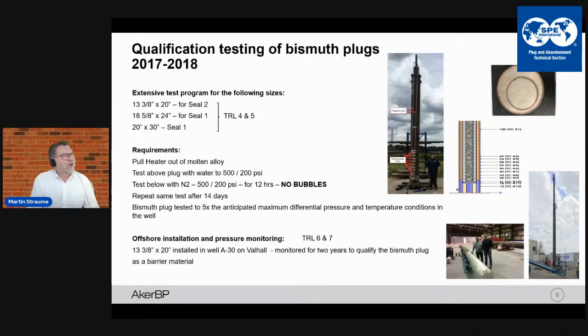So we decided to try bismuth, but before we tried that out, we needed to have a test program. We went to Houston and teamed up with BiSN at that time. BiSN was still there, and we wanted to make a large bismuth plug. This was larger than any bismuth plug they had made before, so we needed to test that out. We were going to have it shallow, as Nina mentioned. It's qualified for shallow water and shallow temperatures, and low pressure. We tested it towards 200 psi first, and then 500 psi with gas from top and below. 500 psi was actually about 5 times as much as we needed to hold back the hydrostatic pressure found below where we set the plugs.